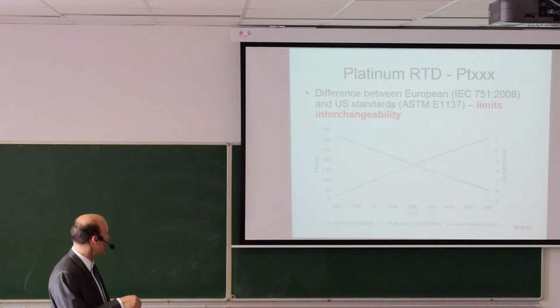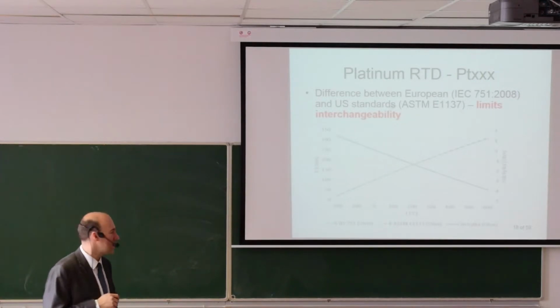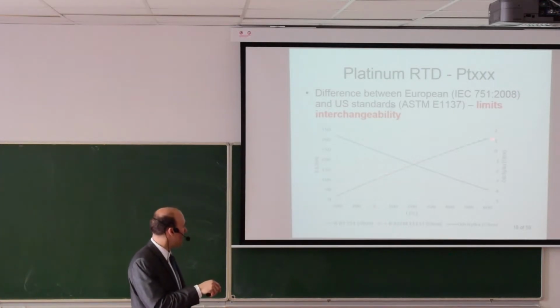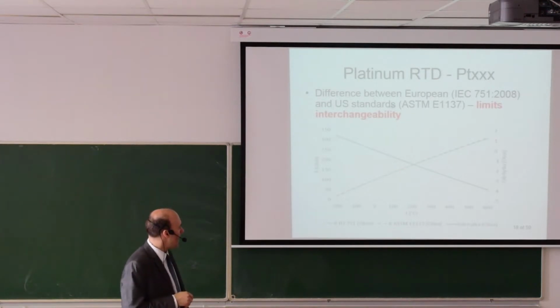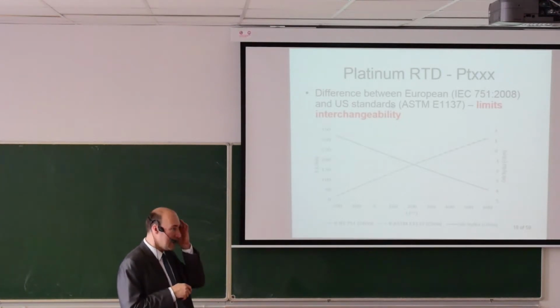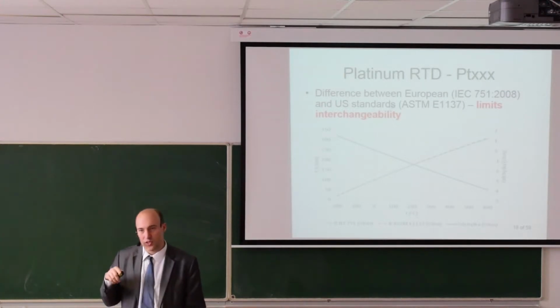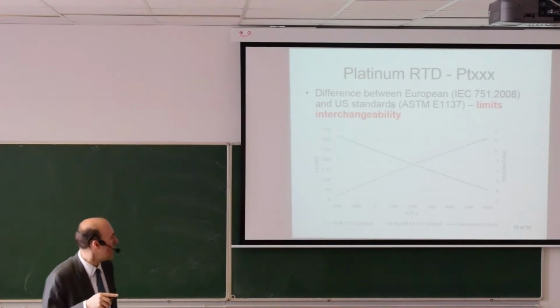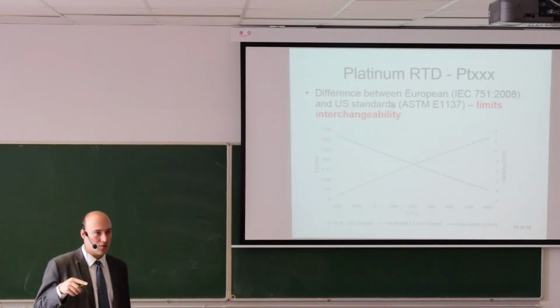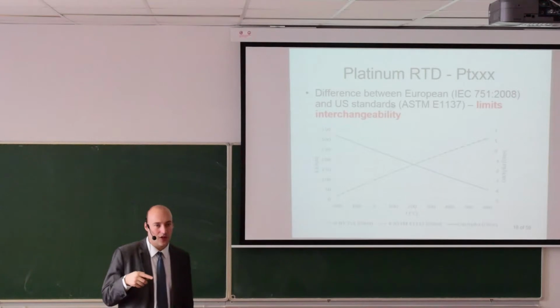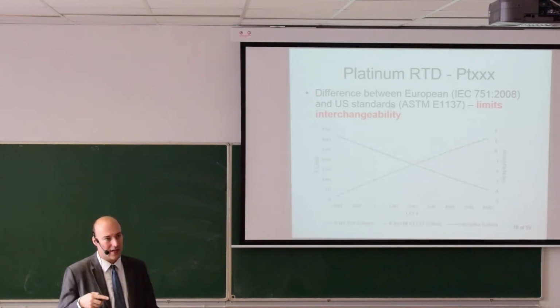This is an example. For 0 centigrades, both standards have 100 ohms precisely. But then there is a difference for larger and smaller temperatures, and this difference is quite significant. Here you see for 600 centigrades, the difference between the American and European standard is about 4 ohms. So 4 ohms, when you look at the sensitivity, which is, let's say, 0.4, will give you an error that's larger than 10 centigrades. So just by using the wrong standard for your application, you may introduce an additional error that is about 10 times larger than the accuracy of your sensor.